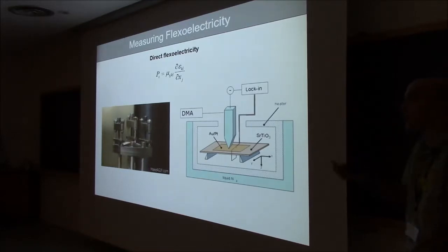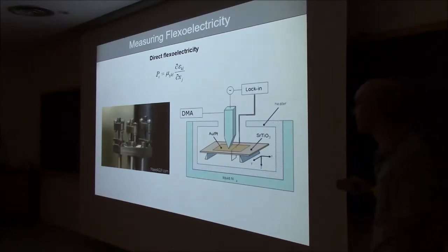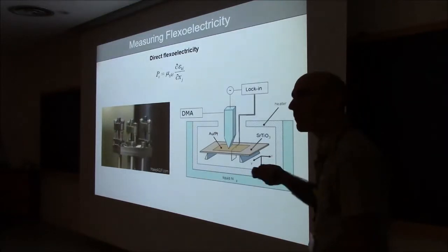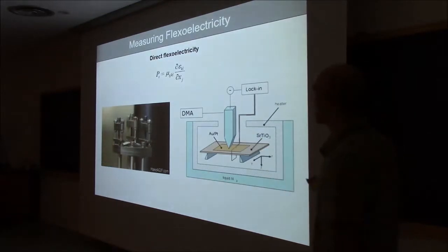Now, how do we normally measure flexoelectricity? Very simply, you bend something and you measure the polarization induced by the bend. It's easier to say than to do. In our case, the bending is done by something called a DMA, Dynamic Mechanical Analyzer.